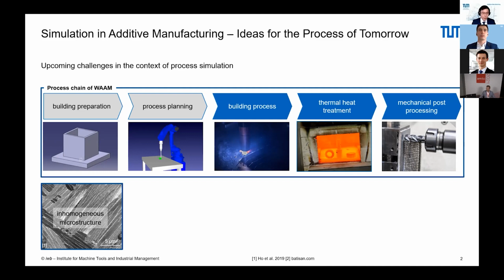During the building process of certain steels, for example, we have large martensite regions on the top layers, but in the lower layers, which have been reheated repeatedly, we have predominantly ferrite regions. So we have a difference in hardness in one part. In order to influence the microstructure, we can also use thermal heat treatments and mechanical post-processing. However, we do wish to know the microstructure inside the part in advance.